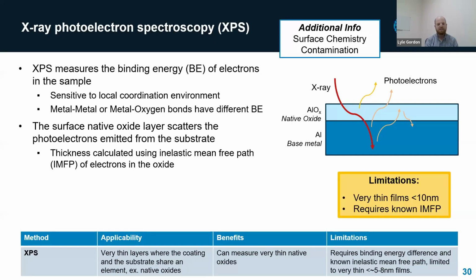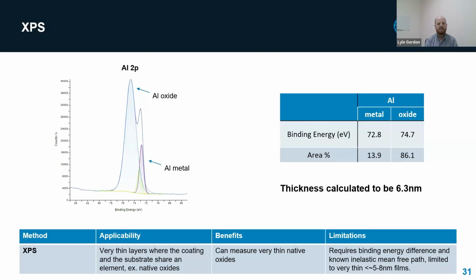So this technique is pretty specialized. It's limited to very, very thin films because you need these electrons to be able to escape, and they have pretty low energy, so like 5 to 8 nanometers. And it requires you to know the mean free path or to be able to simulate that. But this case works well in situations where not a lot of other tools can work. So we'll show just the really simple case of aluminum.